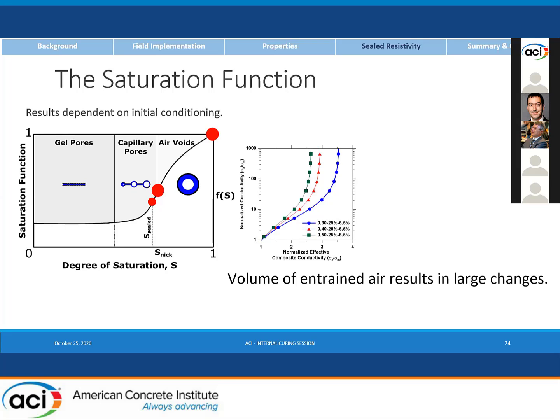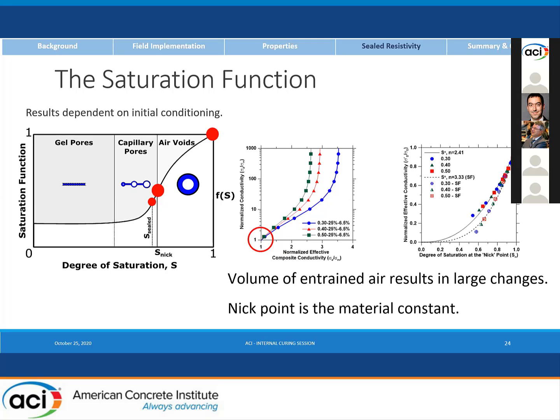So what I will just say is that the fundamental value that we should be comparing against is indeed the nick point, because you can see when we treat the air voids as conductive inclusions, the actual measurement that you get is dependent primarily on the volume of the air that was entrained. And so that's a variable throughout production, and so it needs some estimations with powers. And we can see that if you treat just the contribution of the air voids, it itself fits into an S to the N type of relationship. So these are just theoretical calculations.